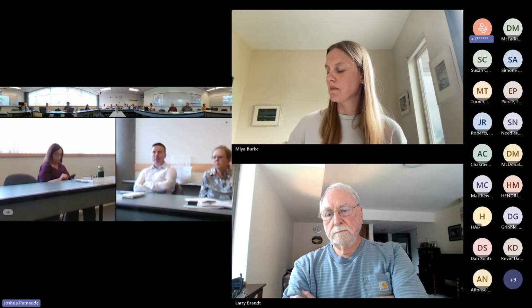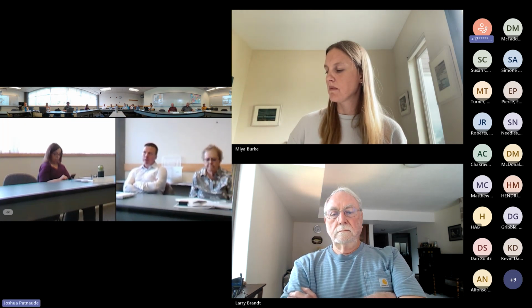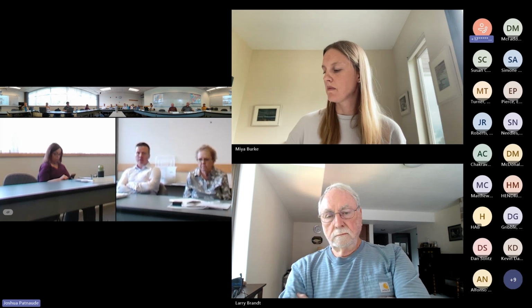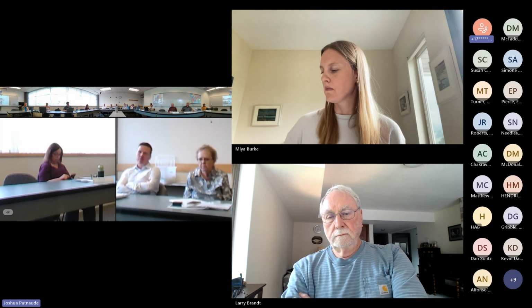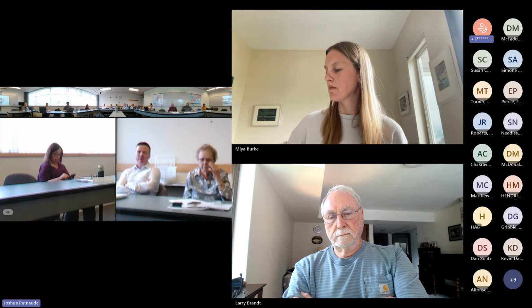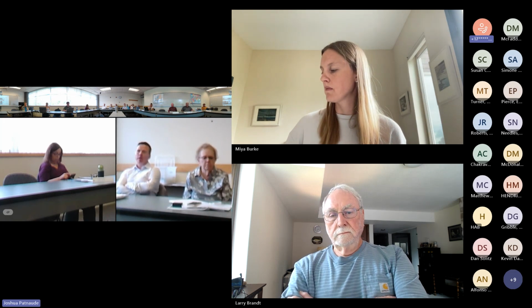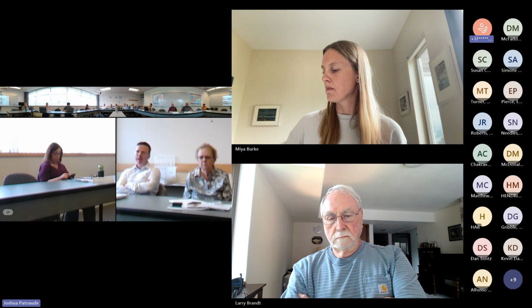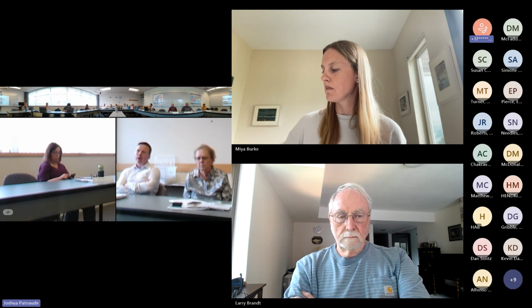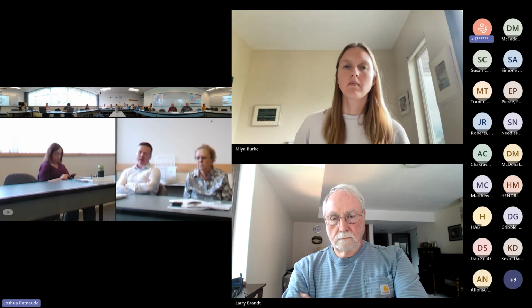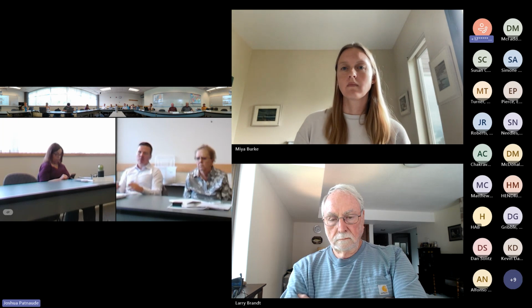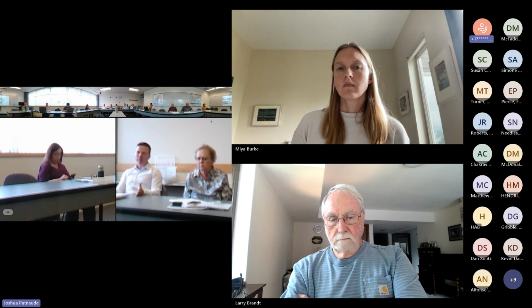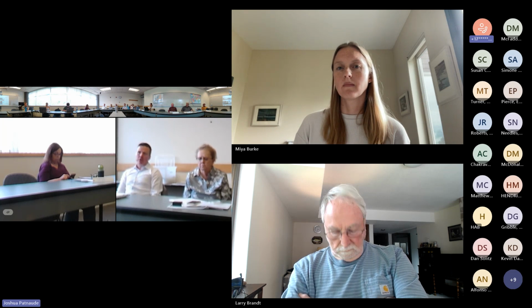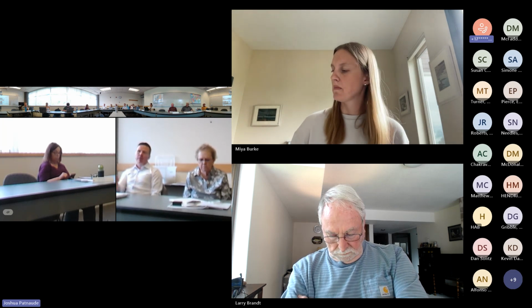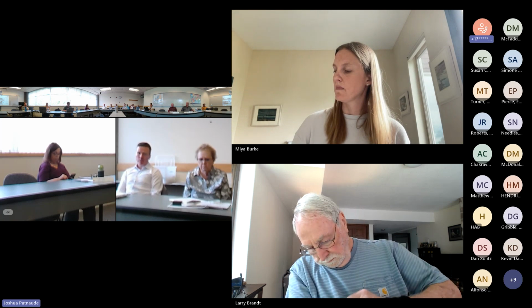I'll give some context to it. The most studied formulation here for use at the Hanford site is called Cast Stone. It's very similar to the original saltstone formulation. It came out of a study that CH2M Hill did back in 2003. For that mixture, which is slag, fly ash, and cement, mixed at a water to binder ratio of 0.4 to 0.6, your volume expansion using that formulation range is about 1.5 to 1.8, and that was the formulation that study looked at.